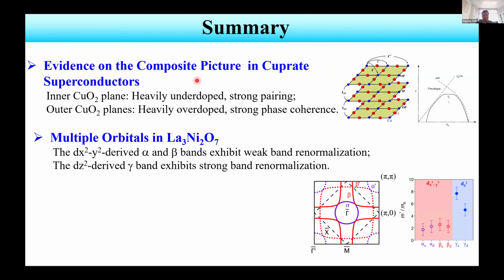We found that in 3-layer cuprates, because we have inner layers and outer layers, the superconductivity can be well described by using a composite picture. In this case, the inner one has a much smaller doping level and a much larger pairing gap. That means it has a much larger pairing strength. But the outer one is heavily doped, and has a very large coherence temperature. So by putting them together, you can form a superconductor with a much higher Tc, in this case around 110 Kelvin.